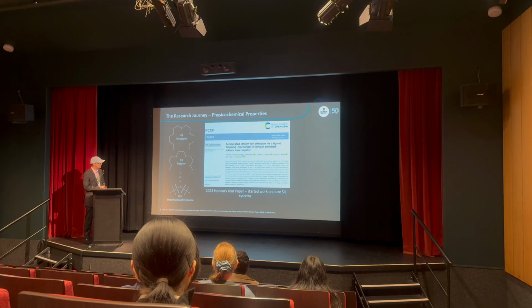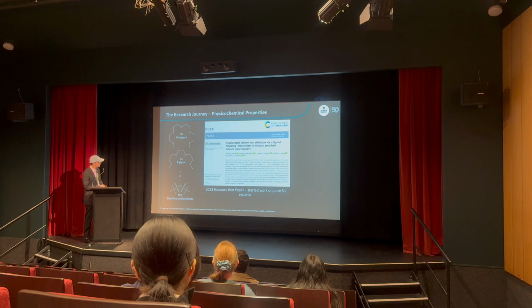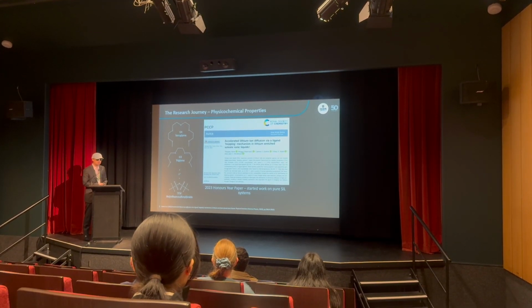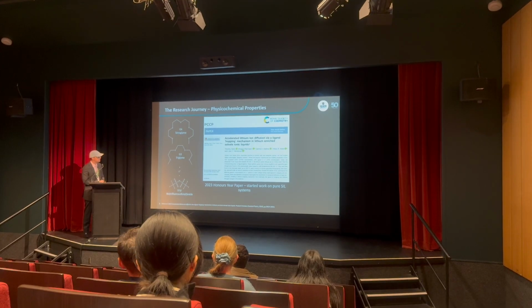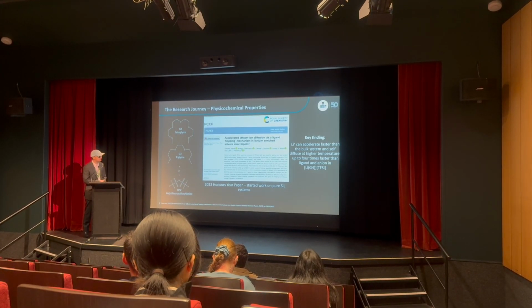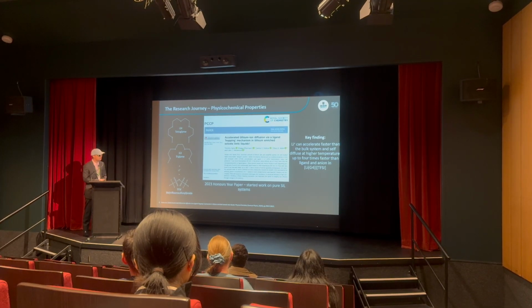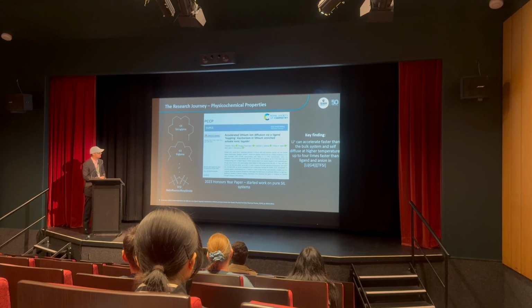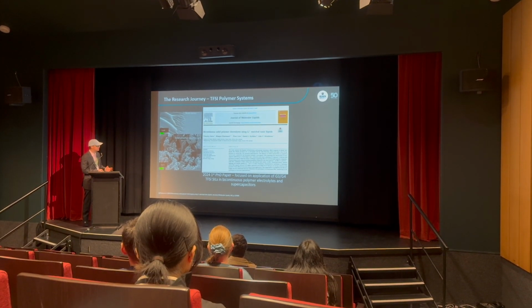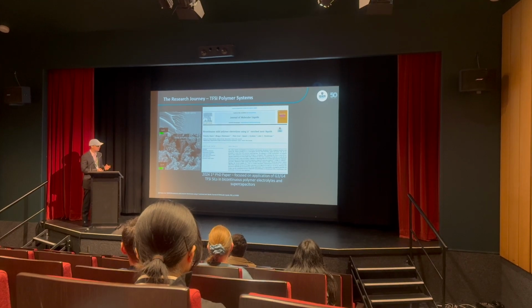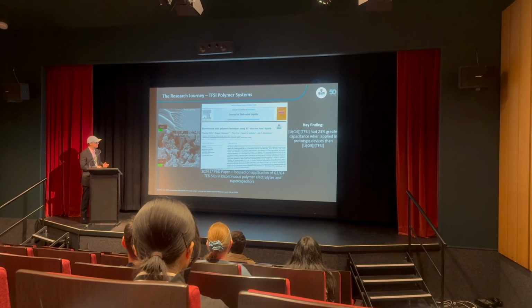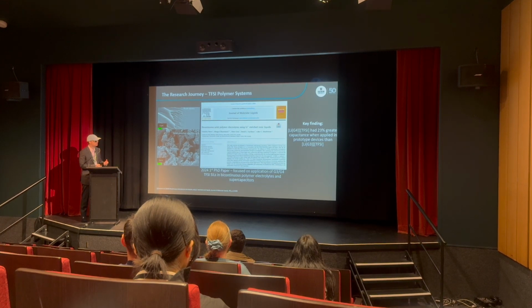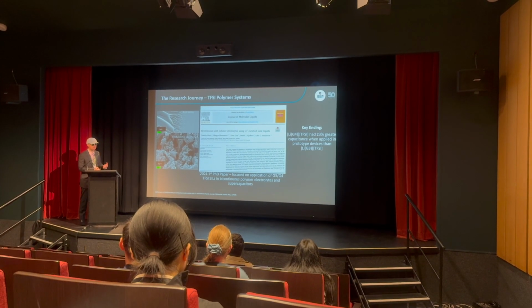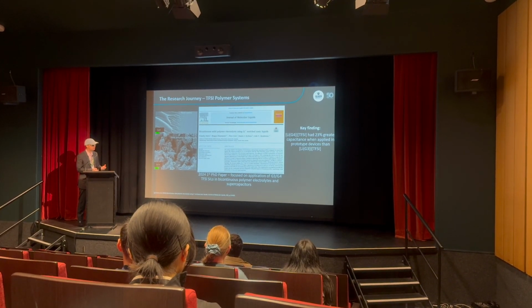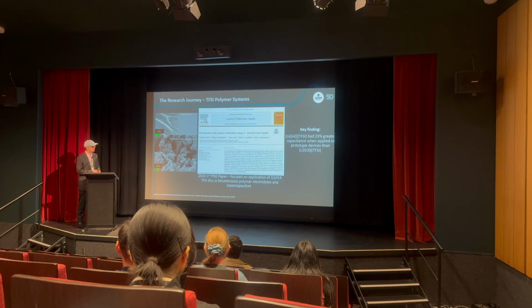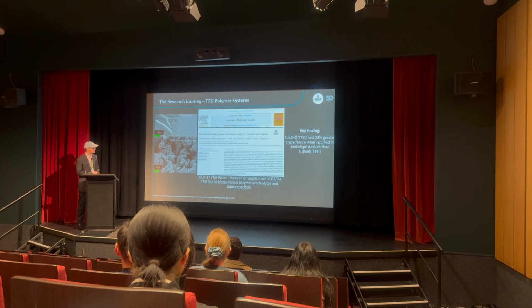Just recapping on the research journey. Going into this, we did some diffusion NMR of the G3 and G4 ligand systems with the TFSI anion. The key finding of this work was that the lithium can accelerate faster than the bulk system and self-diffuse at higher temperatures up to 4 times faster than the ligand and the anion. So this is how this work started. It then evolved into applying the TFSI Solvate Ionic liquids into solid polymer electrolyte systems, and we showed that an optimized electrolyte, the G4 TFSI system, when applied in capacitor devices, had an improved capacitance performance of 23% compared to the benchmark applied in the literature, which is quite exciting.